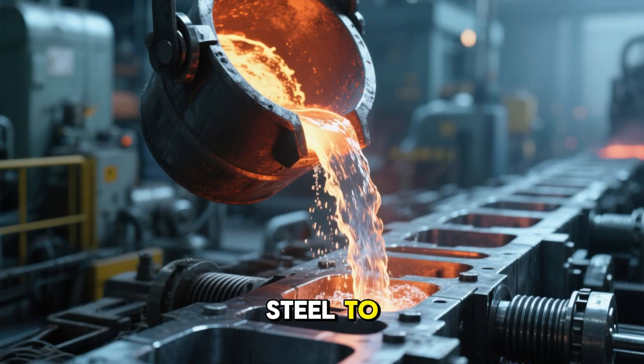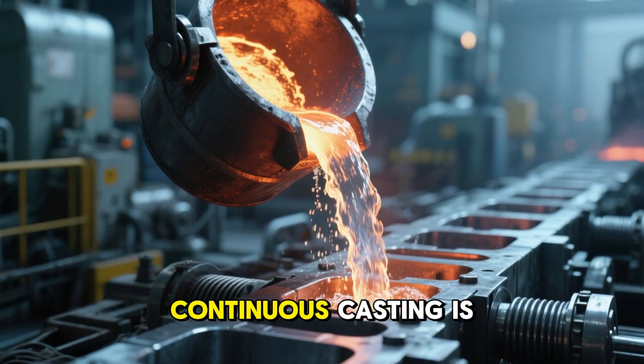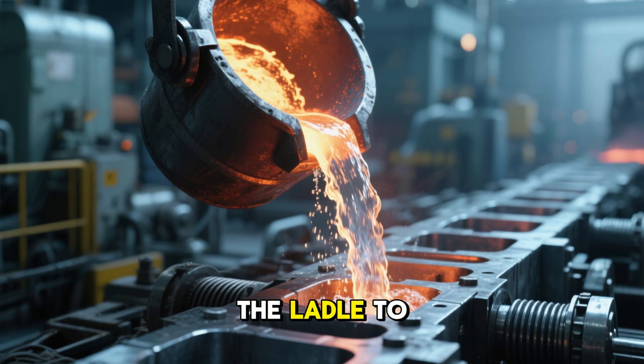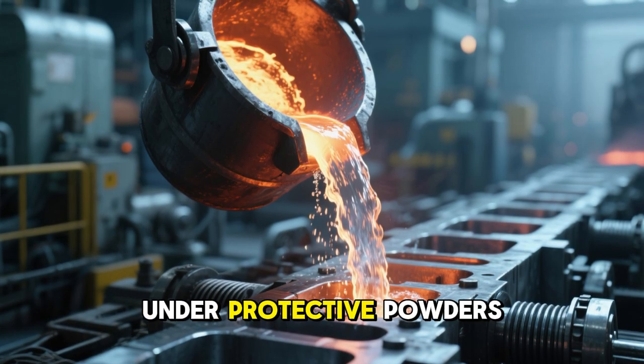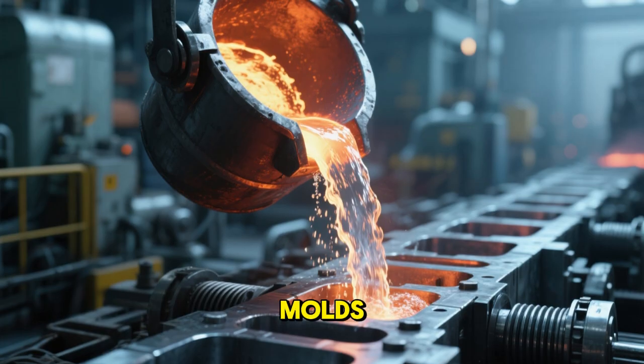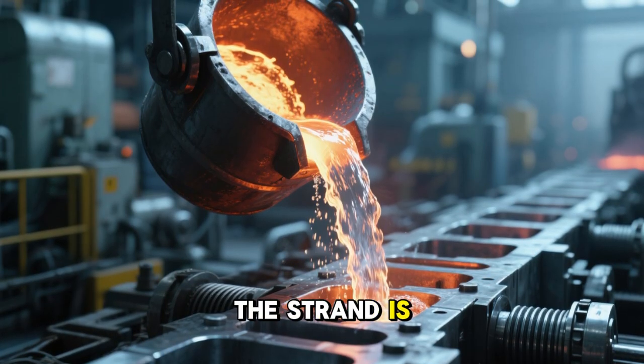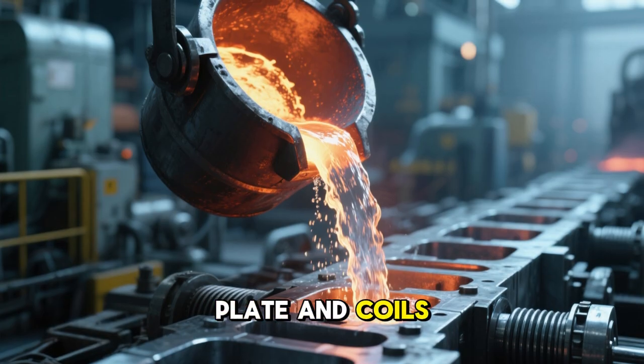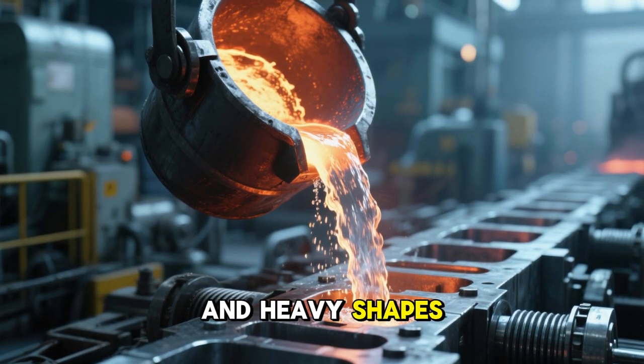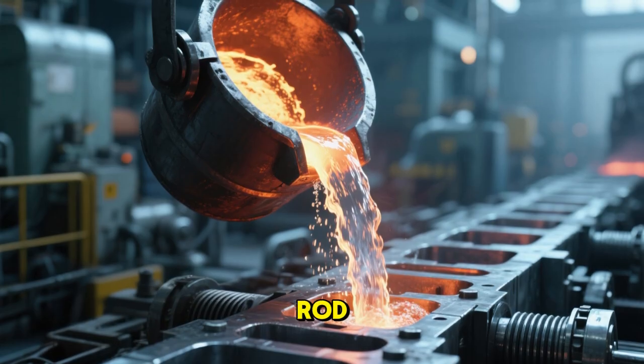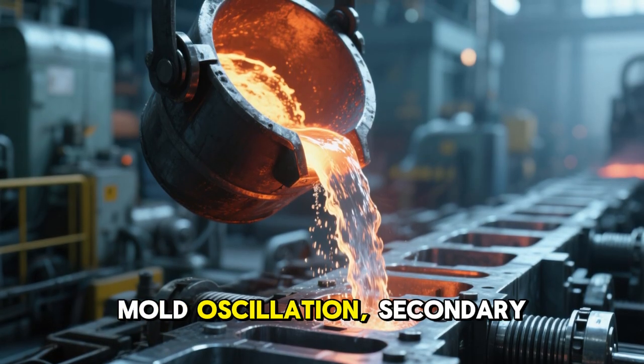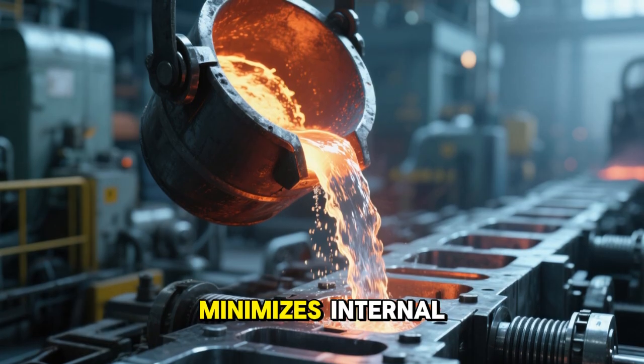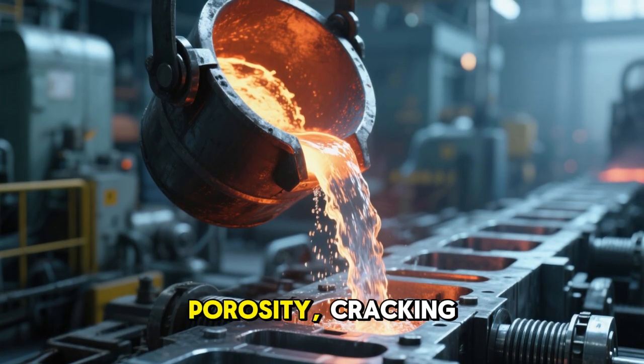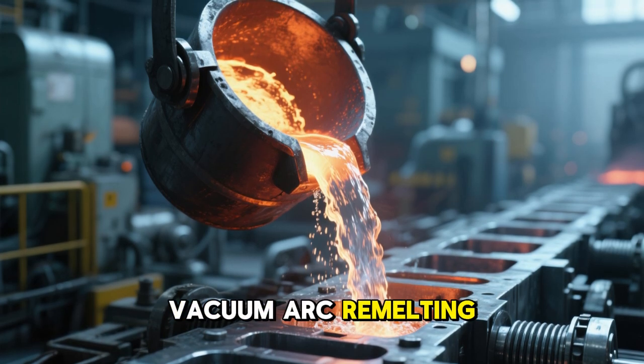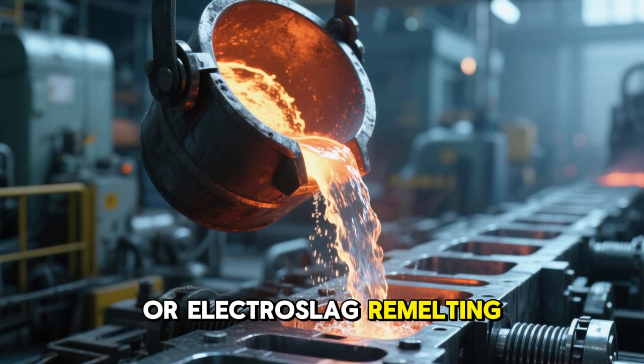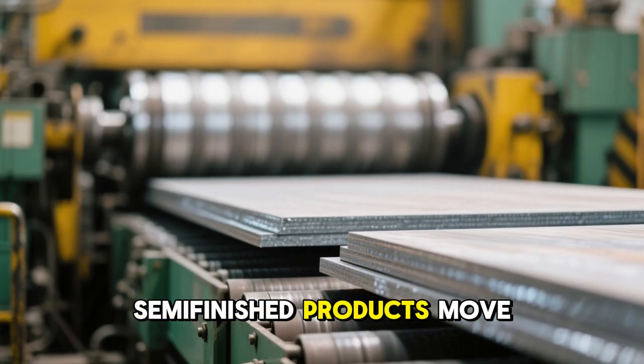Casting converts liquid steel to solid semi-finished forms. Continuous casting is standard. Steel flows from the ladle to a tundish, buffer and filter, under protective powders, then into water-cooled molds. Solidifying from the shell inward, the strand is withdrawn and cut into slabs for plate and coils, blooms for rails and heavy shapes, or billets for bars and wire rod. Control of flow rates, mold oscillation, secondary cooling, and mold powders minimizes internal defects, segregation, porosity, cracking. For special steels, vacuum arc remelting, VAR, or electroslag remelting, ESR, may be used. Semi-finished products move to rolling.